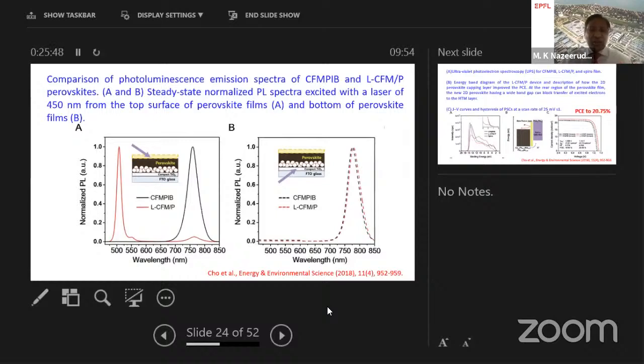Now, another question is, is it only on the top, or does it penetrate through the bulk to the bottom? If you look at the two samples again, that's the reference, the black line, and then the two-dimensional perovskite deposited sample, the red line. If we excite from the bottom side, the two emission spectra are overlapping. So this demonstrates that the two-dimensional perovskite is only on the top of the three-dimensional perovskite. What this two-dimensional perovskite is doing to our perovskite solar cells is shown on the next slide.